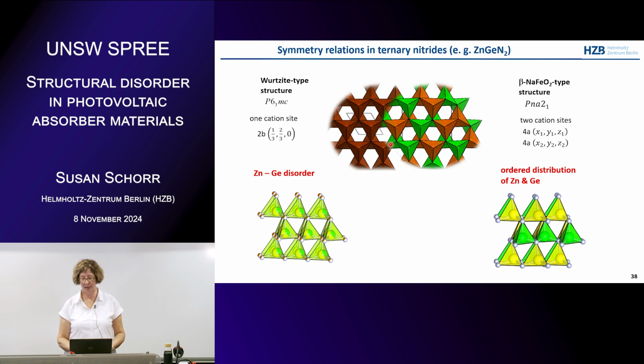The other possibility is this beta sodium ferrite type structure, which is also orthorhombic, where you have 2 cation sites. And this gives you the possibility of an ordered distribution of zinc and germanium. So you have a zinc site and a germanium site. Again, also these compound semiconductors are tetrahedrally coordinated, as we had before.